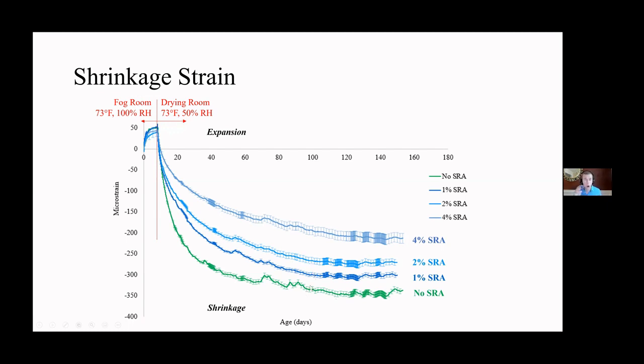You say, whoa. How does this work? Well, the shrinkage-reducing admixture changes the surface tension of the water. That changes the stresses on the concrete. If you didn't understand anything I just said, it's okay. As you add more SRA, you get less and less shrinkage. So as engineers, we usually say, give me the best. Give me the highest dosage I possibly can. And that's actually what most admixture companies recommend you use, right around this dosage.